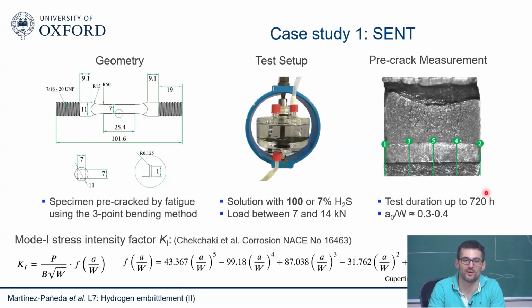And this is a question we wanted to answer, because the industry partners weren't sure how many hours they needed to wait. The standard says 700 hours, but this is a long test. And they said, do we actually need to wait 700 hours? How much does it change, and so forth? And then, of course, you can get the stress intensity factor as a function of the applied load.